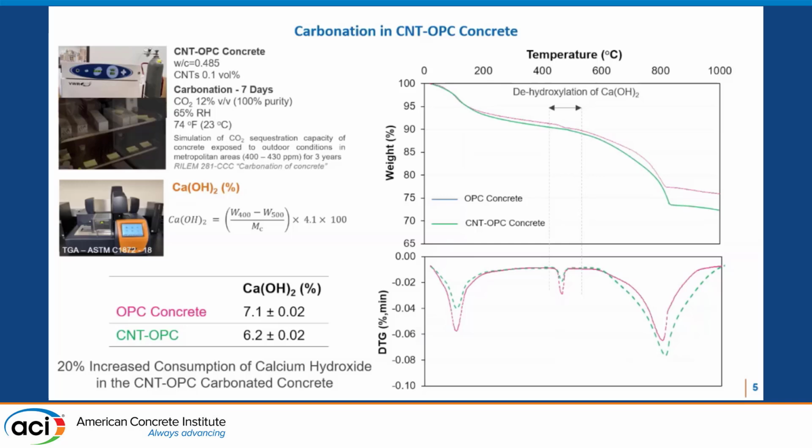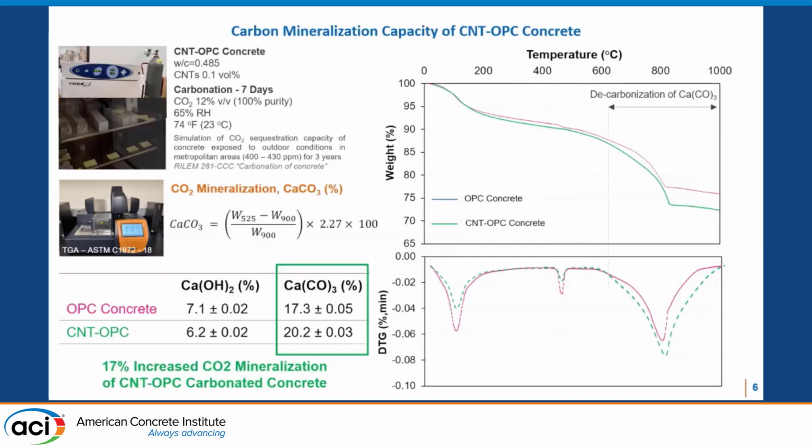Honestly, I didn't think that this was the best that we could do. Perhaps I was too ambitious in that. If we examined a little bit further and see what we are doing and how we are doing it, we measured the mineralization here: 17% increased CO2 mineralization. In concrete, we added experiments with specimens that were outdoors, right outside our lab. This is pretty consistent for the environment that we are talking about.